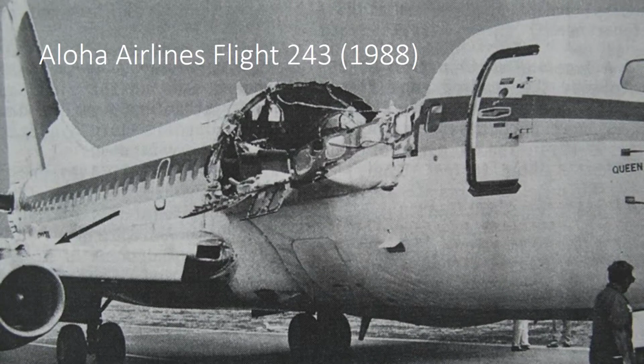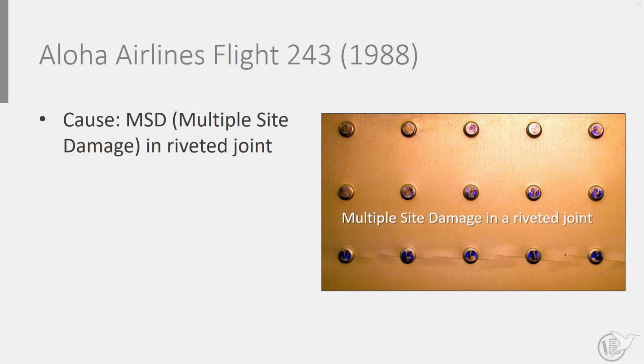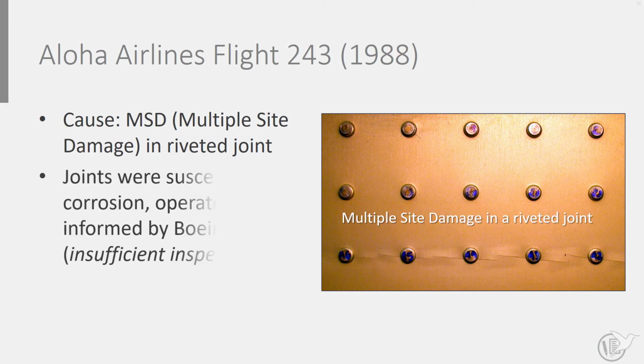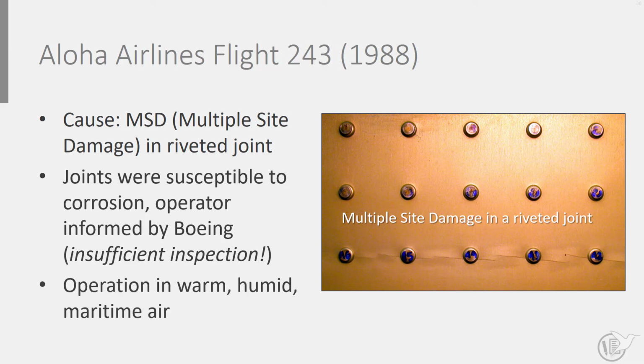Although the damage-tolerant design philosophy significantly improved the durability of airframes, it does not guarantee safety in itself. This is illustrated by the Aloha Airlines accident, where a Boeing 737 lost a significant portion of the upper fuselage structure. This failure was caused by multiple site damage in the riveted longitudinal fuselage joints. These joints were susceptible to corrosion because the aircraft operated in a warm, humid maritime environment. The operator was advised by Boeing to inspect these joints, but it did not perform the required structural inspection, resulting in failure. The combination of fatigue damage with environmental influences has resulted in that airframes these days should be designed damage-tolerant and with sufficient durability.